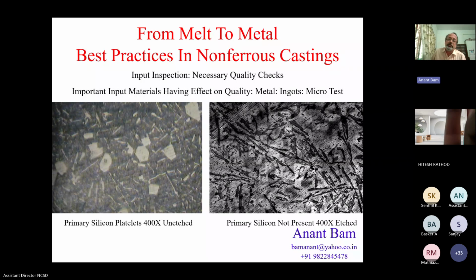Now this is microstructure. Everybody may not check the microstructure of the ingots, but during the fracture test, if you find bright white spots, then it's recommended that you take a micro test of that ingot. On the left-hand side, the platelets which you see are platelets of primary silicon, the wafer-like things. And the needles are eutectic silicon, or the dissolved silicon. On the right-hand side, you can see that primary silicon is not present and only the needles of eutectic silicon are present. So the right-hand side structure is more preferred, and the left-hand side structure is not preferred. So if you find bright spots, go to the previous slide.